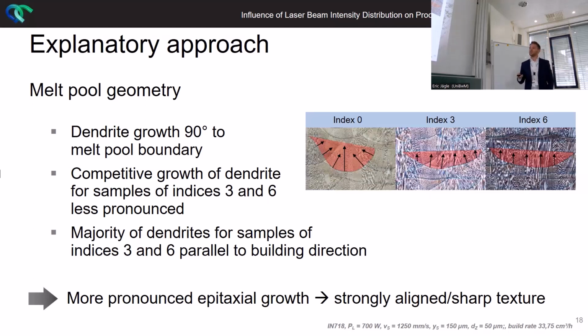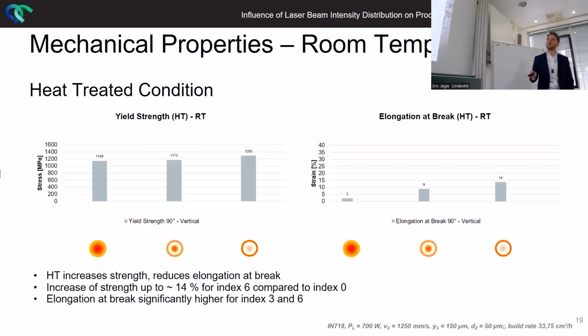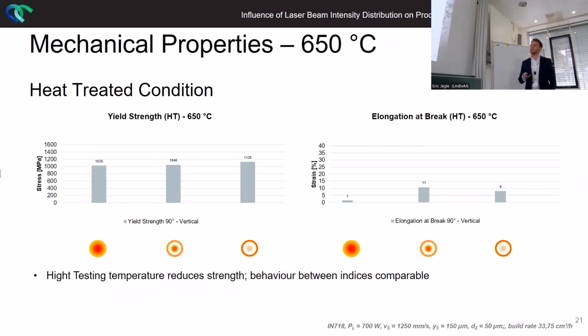And then we asked the question if it's only possible for this aspect condition or this orientation? And the answer is no. We did some further experiments in the heat-treated state, and even in the heat-treated state, we could see this trend or this phenomenon of a slightly higher tensile or yield strength, while the elongation at break was much higher for index 3 and index 6 samples. And even at higher testing temperatures, we could see this trend here for 650 degrees C tested tensile specimens.